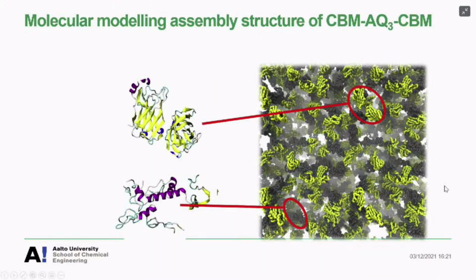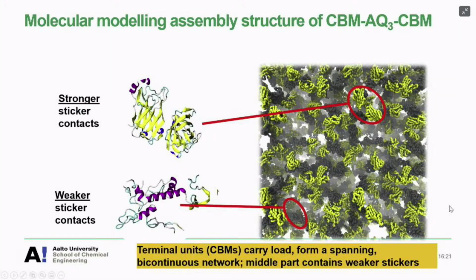condensate structure. And to show that, like how the end unit contacts or the alpha helical clusters show in this big simulation system, there are a couple of examples there. What we run into here is that there are stronger sticker contacts between the end units, then there are weaker sticker contacts, and the crucial thing here is that we run into timescale issues with the relaxation of the system and the dynamics of the system.